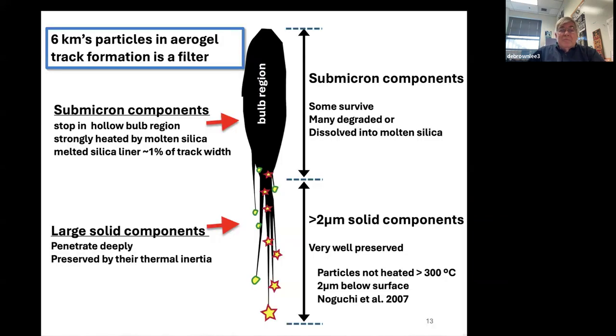We collected particles by impact into this silica aerogel, so you can think of a track. A particle comes in from the top. The smaller particles don't go as deeply into the aerogel, and they're stopped in what we call the bulb region. The larger particles penetrate all the way down to the tips. What I'm going to talk about mostly today is the things found at the bottom of the tracks, particles larger than 2 microns, and these are well preserved.